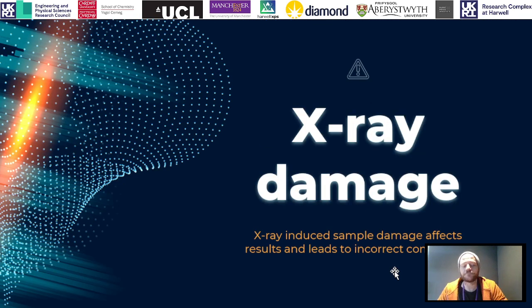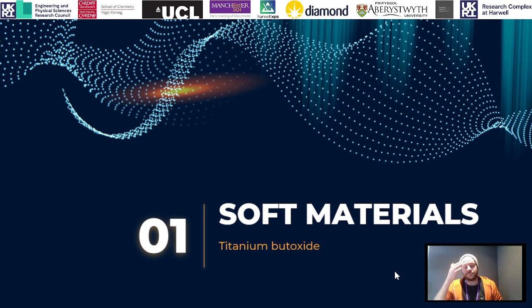So if you're not familiar, when you have materials in a UHV system, X-ray and electromagnetic radiation can actually do some kind of damage to your systems. Exactly the processes of those depend a little bit on what the material is, but of course if we do have any kind of damage like this, it is incredibly important to know what damage is being caused and how we can minimize the impact of this, because of course if we do have damage changing some of the chemistry in our surfaces, then this could lead us to some erroneous conclusions about the materials that we're working with. So we do need to look to overcome these, minimize those.